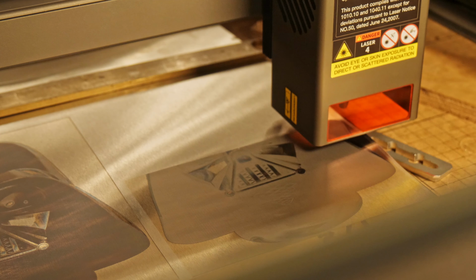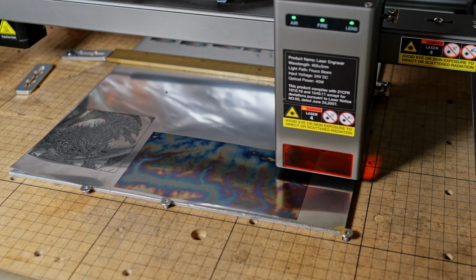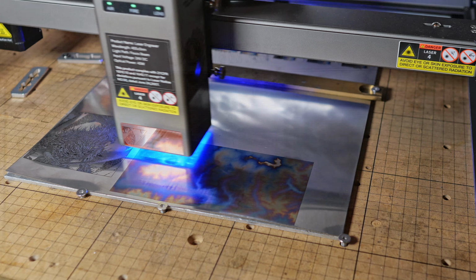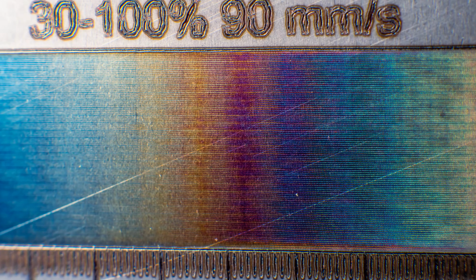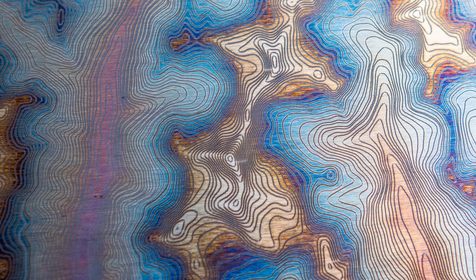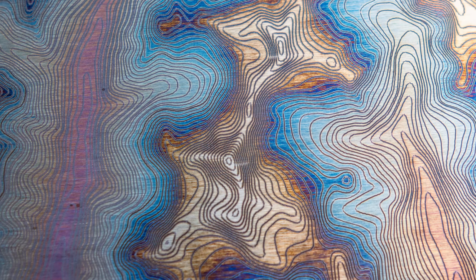This is a 40 watt diode laser, and surprisingly enough, it can engrave and mark stainless steel. But far more interestingly, by varying the power of the laser, I'm able to very precisely control the heat of the surface of the steel underneath the laser beam, allowing for the production of some really beautiful colours. Unlike pigments or dyes, these colours are never going to fade or be damaged by ultraviolet light from the sun, since they're a physical interaction of light with the surface.